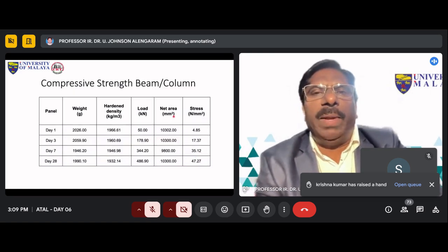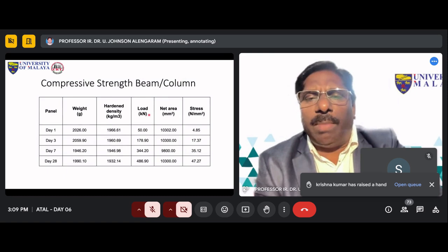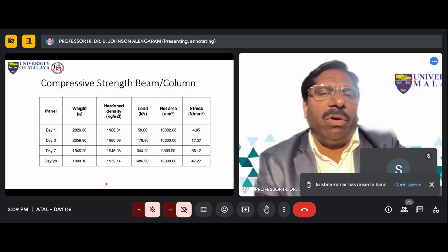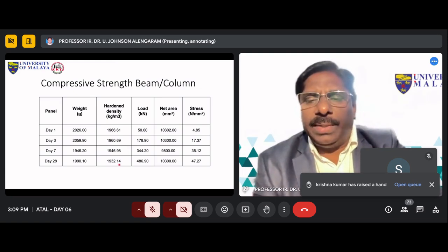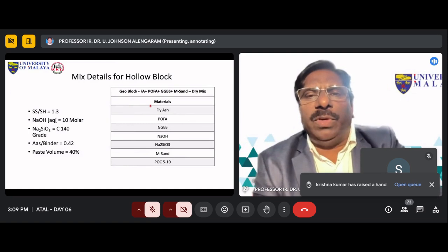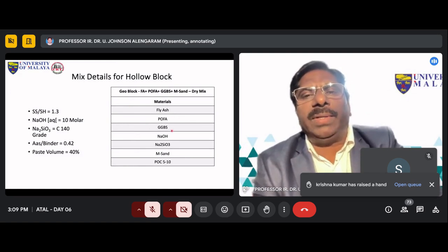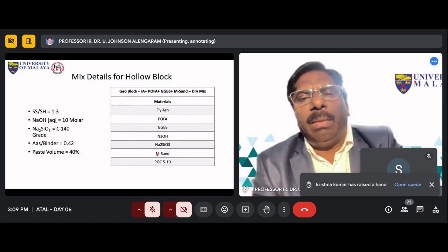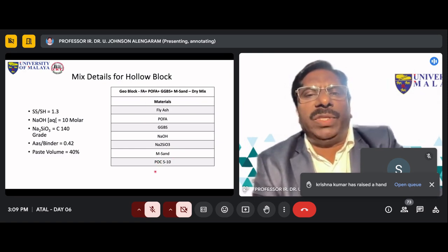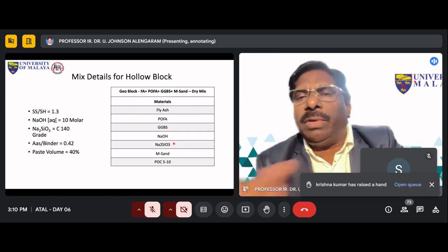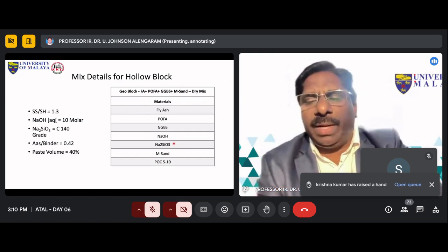So then when we built the beam and column, we had a strength of 47 megapascal, and the lightweight concrete below 2,000 kilogram per meter cube is called lightweight concrete. And we used fly ash, palm oil fuel ash, GGBS, and sodium hydroxide, sodium silicate, manufactured sand, and palm oil clinker as an aggregate. You see, no conventional material, no mining sand, no river sand, no ordinary Portland cement, and so on.